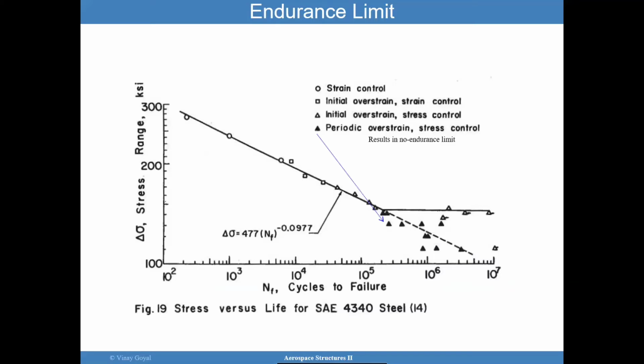Another point I want to make is that if you look at the steel situation, the y-axis here is a stress range. You're going to see SN curves in many different ways: alternating stress, stress range. It's important that you have the right data and you're comparing to the right stuff. Here is stress range compared to cycles to failure. If you look at a situation where there's a periodic overstrain, look at how the endurance limit is gone, and I start having finite life. If I have an initial overstrain and I do strain control, for the most part you have an endurance limit, but at 10 to the 7th, you start losing it. So if you have periodic strain issues, there could be a situation where the endurance limit no longer applies.